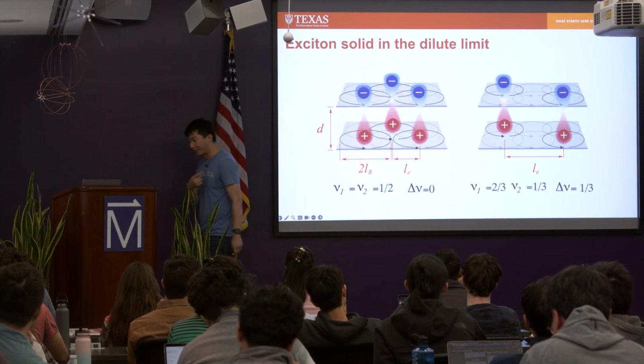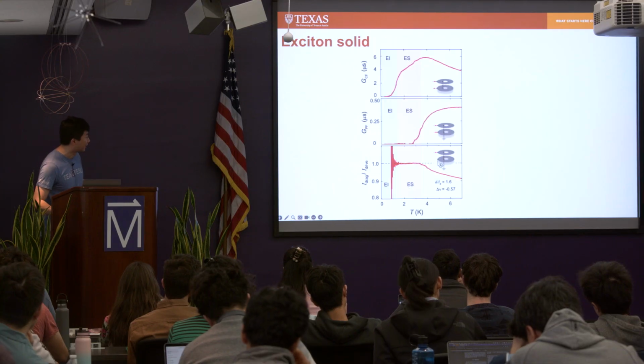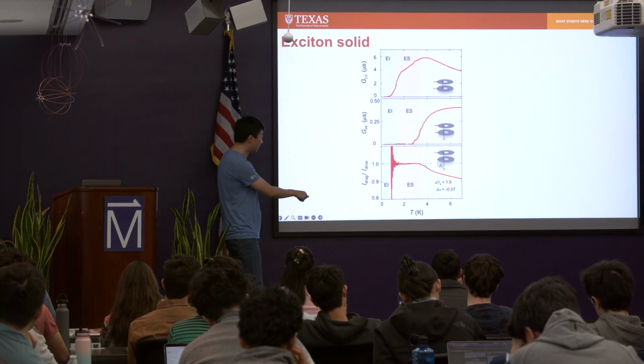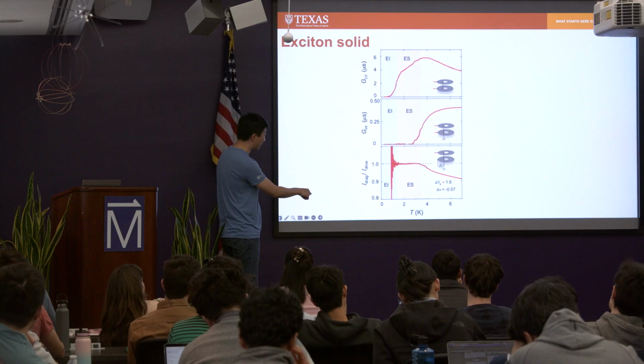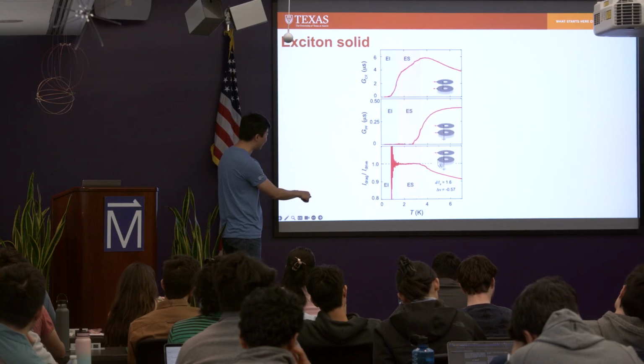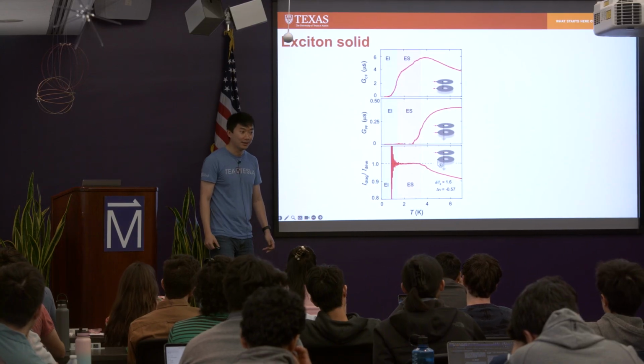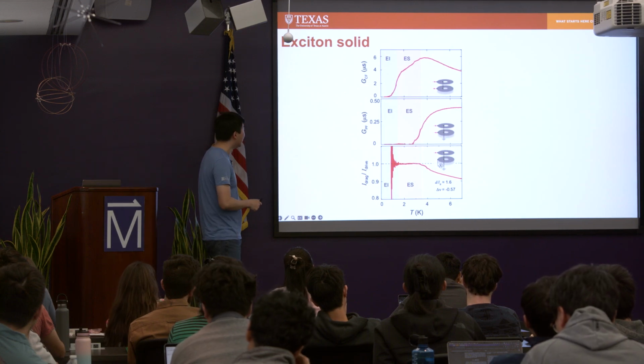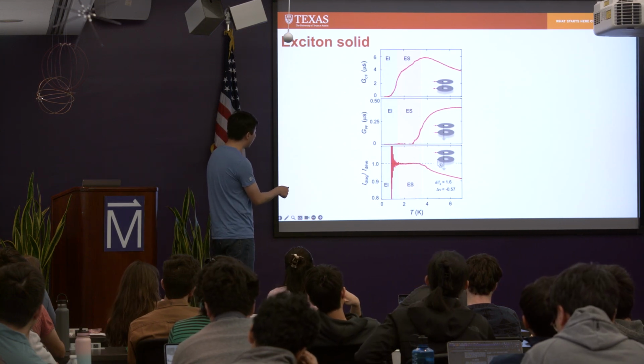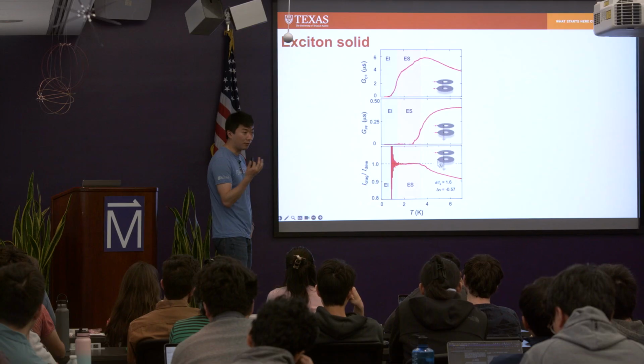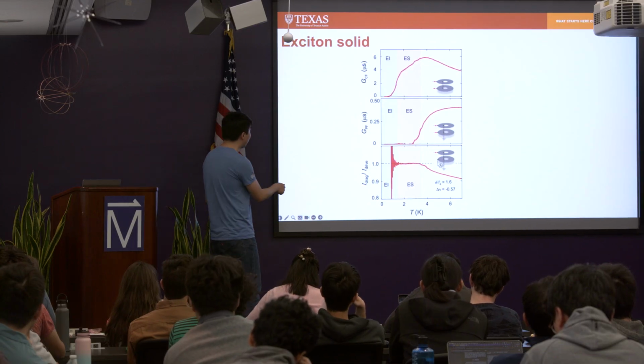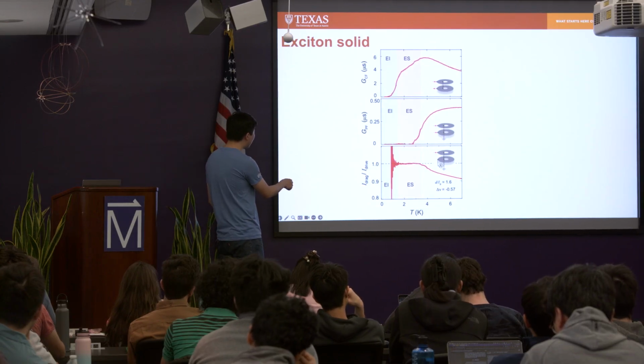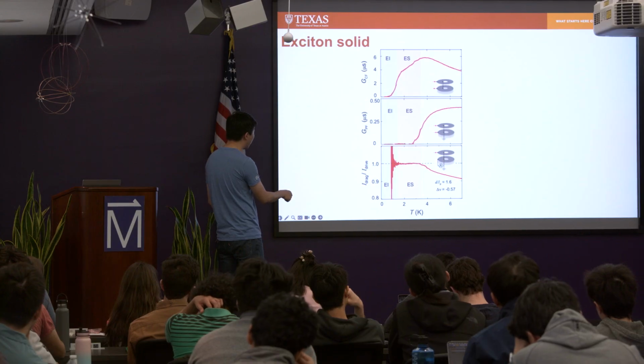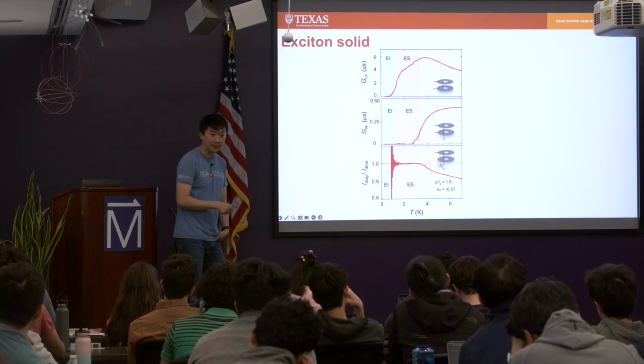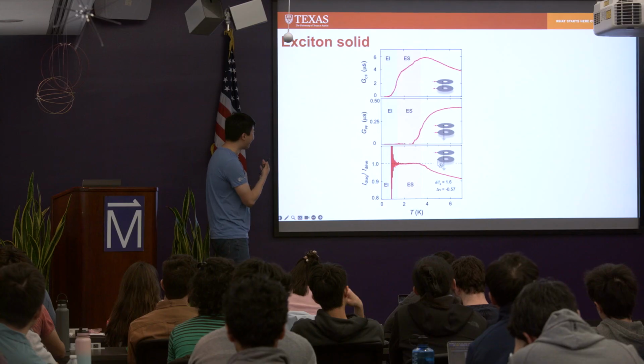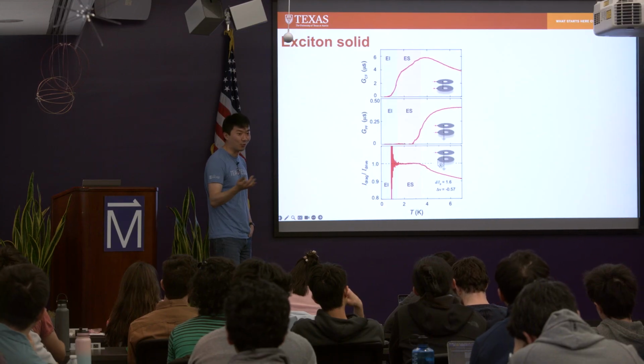And then, so that's what we did. And in the very dilute limit, there's a very interesting response, right? This is interlayer imbalance about -0.57. So it's already in the very dilute limit. I'm showing Corbino measurement result at total filling of 1, so still excitonic state, right? At the very low temperature, counterflow shows 0 conductance, parallel flow shows 0 conductance, right? It's an insulator.